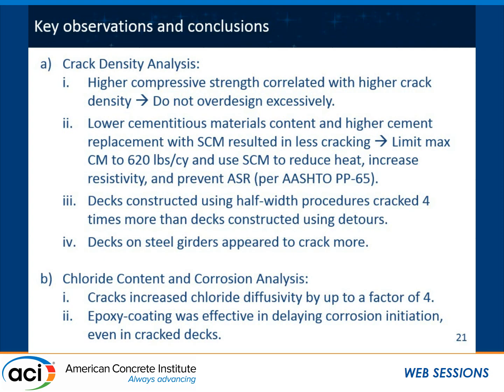Did you also measure the crack widths, the widths of the cracks? We did measure, I would say, on a limited number of cases, not on all of the 200 bridges and across the whole bridge. That was one of the things that we learned early on in this project: crack mapping on an actual in-service bridge especially is not trivial, and it's quite costly.